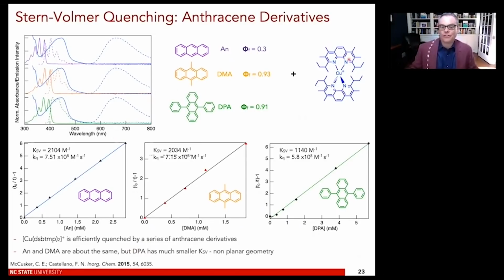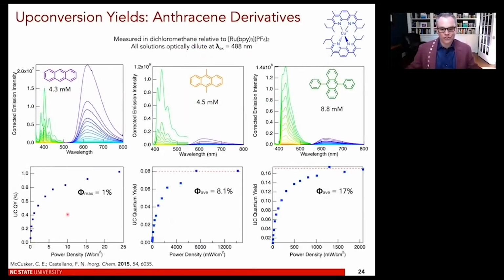And we approach this all the same way. You take your copper MLCT excited state. We used a variety of anthracene-based acceptors here with different fluorescence quantum yields. And you can see that we do Stern-Volmer analysis. We know how to optimize the quenching. We know how to optimize light absorption. We know how to do all of this. And then you get to these plots, which are very typical. We see upconversion in all three acceptors, and we maximize the quenching, which is why those are selected at different concentrations. And then when you look at the quantum yield for upconversion, and this is the normalized quantum yield, so these are all multiplied by two.